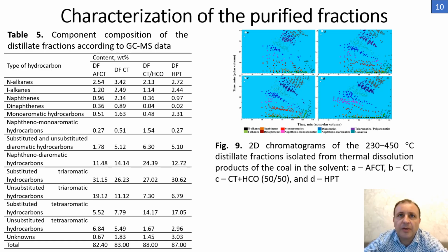Gas chromatography mass spectrometry was used to study the molecular composition of the neutral fraction obtained from distillate fractions. We used a combination of polar and non-polar columns, which work well for mixtures consisting of condensed naphthenic aromatic compounds. We identified between 391 and 558 organic compounds in the samples. The main components were various aromatic hydrocarbons with 2 to 4 condensed rings and hybrid hydrocarbons.